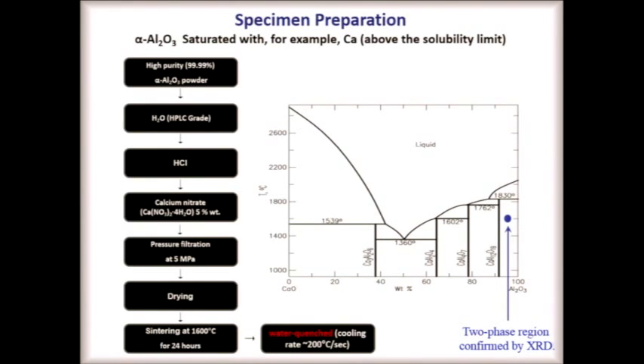There's two tricks. One is preparing the specimen. For that, it's actually easy. We just dope the material so that we're in the two-phase region. In this case, I'm not showing the magnesium. I'm showing the example with calcium. And by putting ourselves more or less here, we have a two-phase mixture of alumina and calcium hexaluminate. Under the condition that we anneal this for a long time and we've reached a homogeneous distribution, we're at equilibrium, then the alumina must be saturated with calcium, and the rest of the calcium is in the calcium hexaluminate. That's undergraduate level phase diagrams.